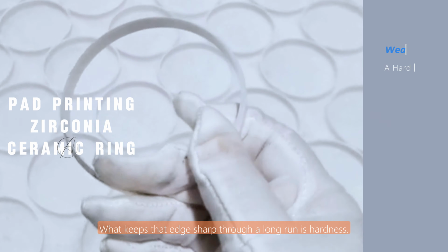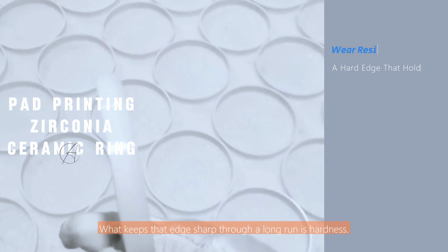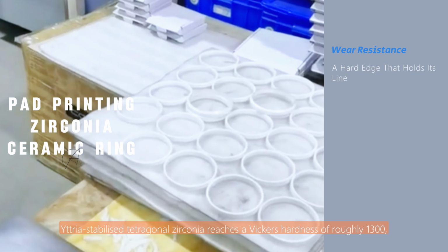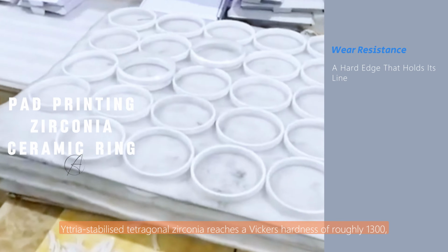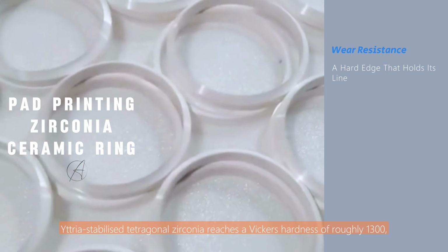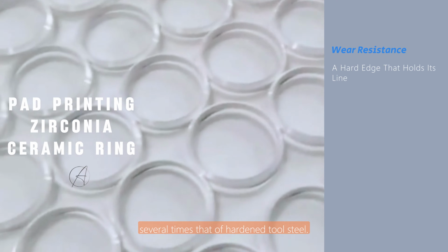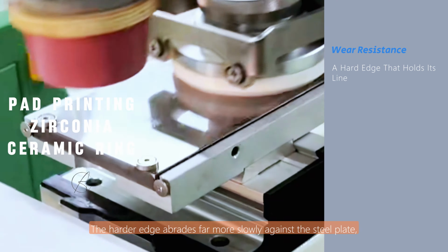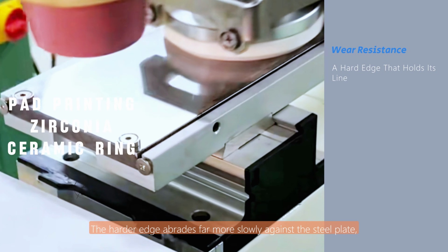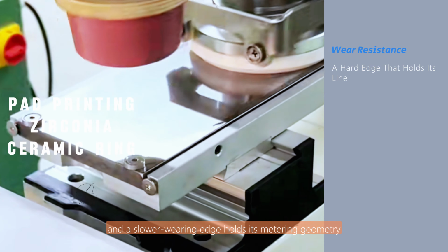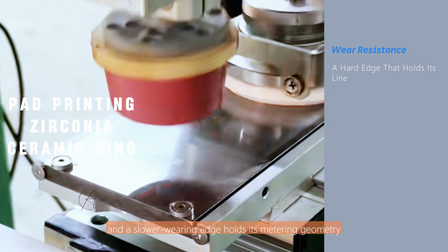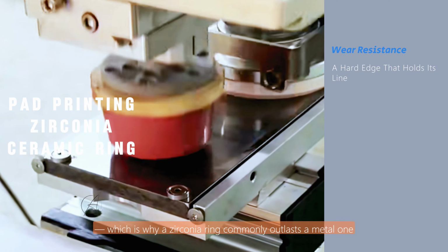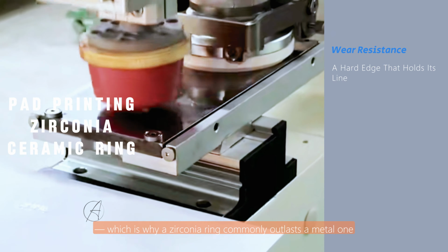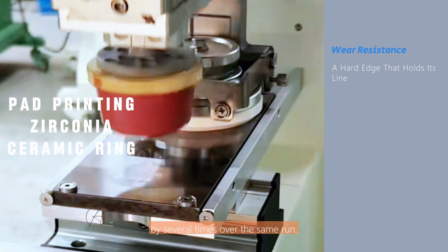What keeps that edge sharp through a long run is hardness. Yttria-stabilized tetragonal zirconia reaches a Vickers hardness of roughly 1,300, several times that of hardened tool steel. The harder edge abrades far more slowly against the steel plate, and a slower wearing edge holds its metering geometry, which is why a zirconia ring commonly outlasts a metal one by several times over the same run.